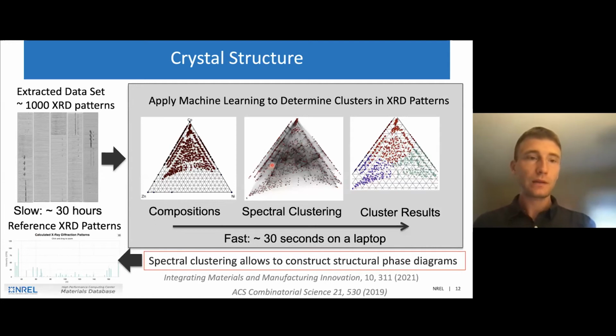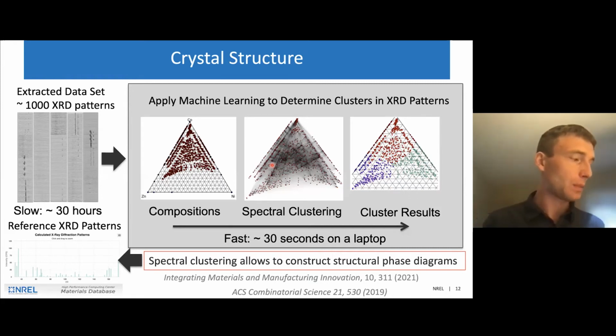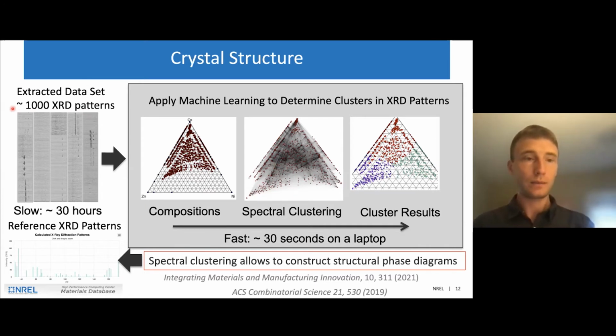We have also found ways to process the large amount of crystallographic information that we have in the form of X-ray diffraction in our database, to get something more meaningful than just an X-ray diffraction pattern. We have more than 100,000 X-ray diffraction patterns available, and this plot here shows a very compressed selection of only 1,000 of them. So that's just a fraction of what we have in the database. That corresponds to one specific material system that contains zinc, nickel, cobalt, as well as oxygen.